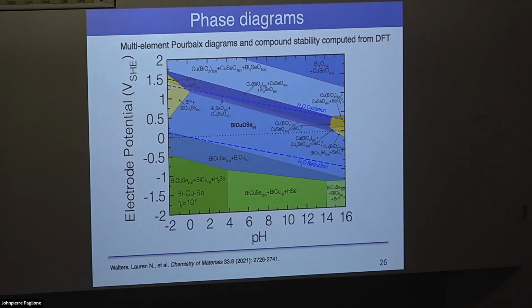So one thing I mentioned previously was the push for predictive materials design using DFT and ab initio methods. This is a very recent paper in Chemistry of Materials last year. Basically what they were trying to do here is combine multi-element Pourbaix diagrams. Most of the Pourbaix diagrams you'll see in the literature are just for one element, like the ones I showed you, like gold or iron. So they combine multi-element Pourbaix diagrams and computed compound stability using DFT or other techniques, and actually predict, at different regions in your electrochemical potential versus pH phase space, exactly what phases are going to form. This is an example of a multi-element Pourbaix diagram combining DFT for bismuth copper oxyselenide. So you can see all these different.